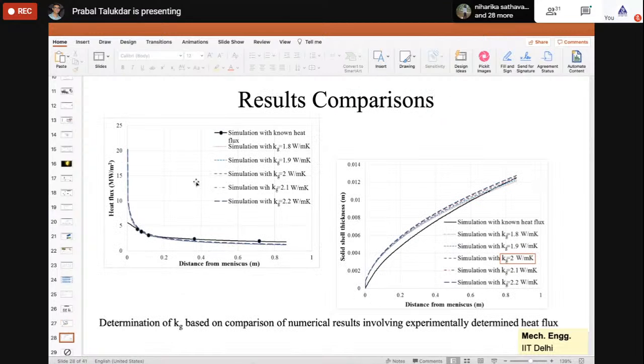So these are some simulations which we have done, and if you see the Kg values, we have varied the conductivity of gases from 1.8 to 2.2. We don't have to use very drastic ranges of Kg value, it's only from 1.8 to 2.2. This is the simulation with known heat flux, which we already know from our experimental data. And if you see, they all match, and I think the value of Kg equal to 2 is considered